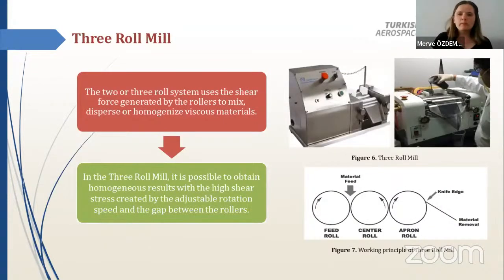And the three-roll mill. The three-roll mill system uses the shear force generated by the rollers to mix, disperse, or homogenize viscous materials. With the three-roll mill, it's possible to obtain homogeneous results with the higher shear stress created by the adjustable rotation speed and the gap between the rollers. The three-roll mill is shown in Figure 6, and the working principle of the three-roll mill you can see in Figure 7.